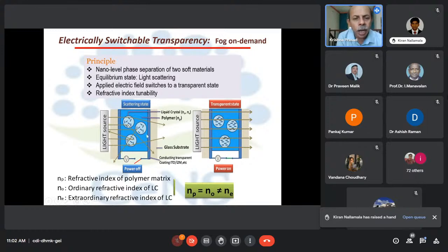So I have one, the equilibrium state here. The blue patch around is a polymer which has the refractive index N sub P. The droplets inside have either Ne or N naught. Wherever it is N naught, of course, it coincides with the polymer refractive index. But because of the presence of Ne in most of the directions, Ne is not equal to Np. Since there are different refractive indices, any light that is put on the system gets significantly scattered. So the panel is a scattering panel.